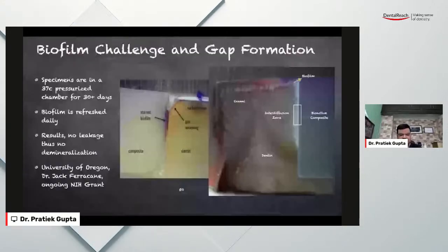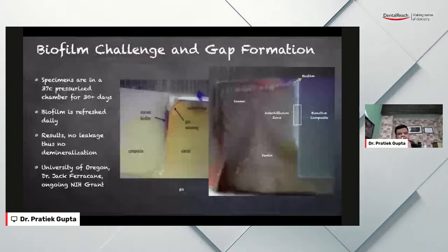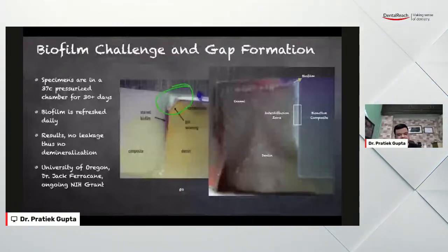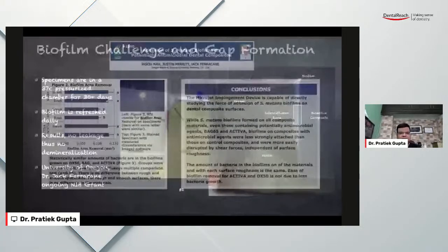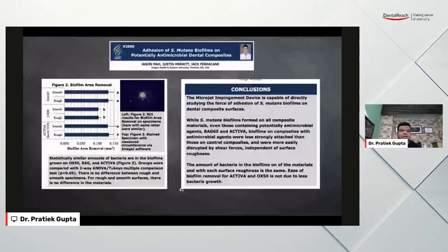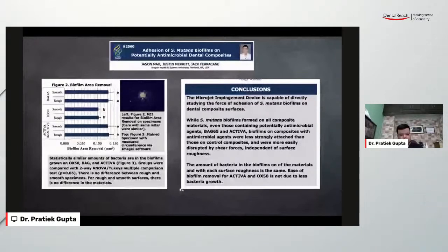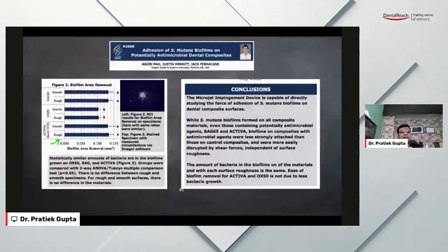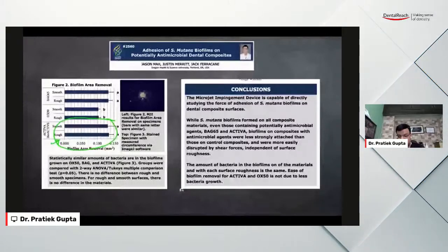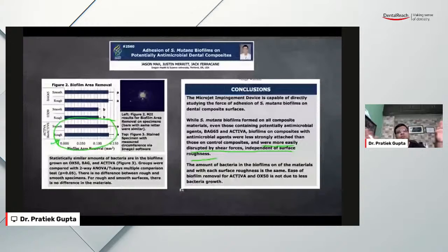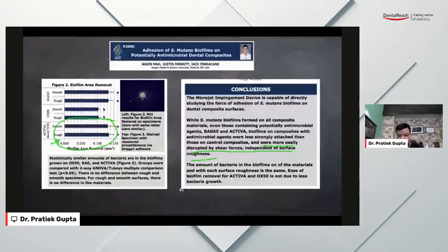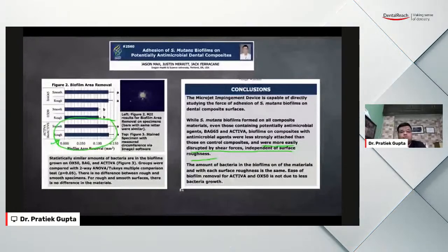Then you have the biofilm challenge, and the moment you have biofilm that starts to develop around the composite to tooth interface, over a period of time, this will disintegrate and you have open margins. You develop open margins, you have an area which is full of cariogenic bacteria. Now, studies which show that biomaterial, or bioactivity, is probably the answer, show you that even though you have Activa in this, you still had oral biofilm develop around Activa also. But these were more easily disrupted by shear forces on the Activa. That means the moment you brush, the biofilm would get washed out. It would not remain. But on the composite, they were more strongly attached, you could hardly remove them.